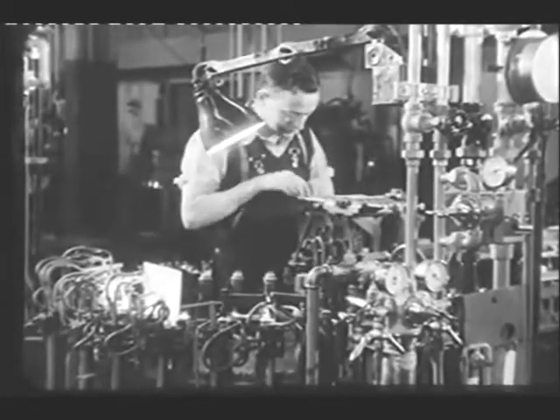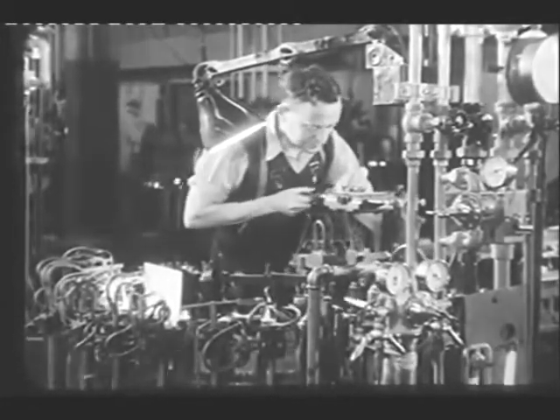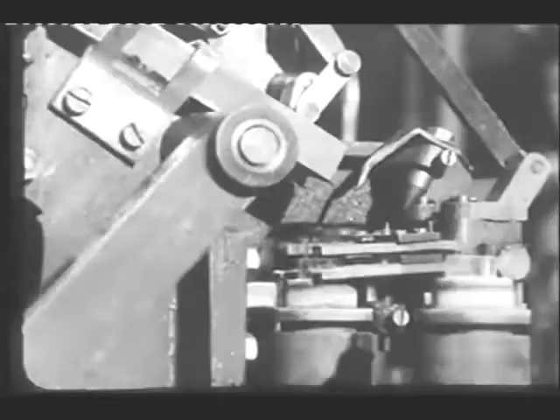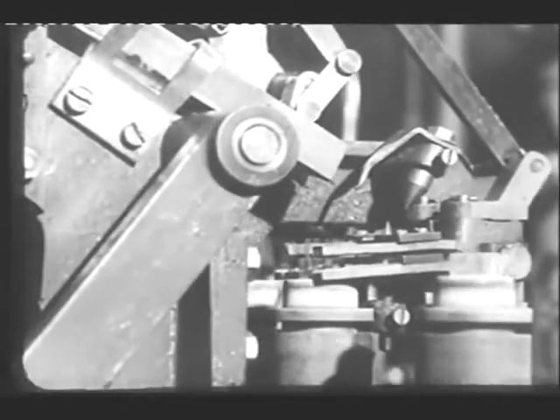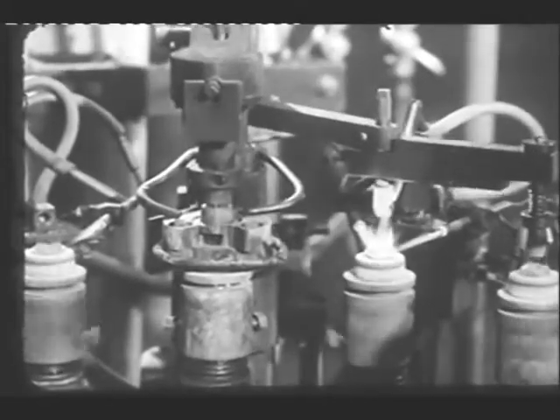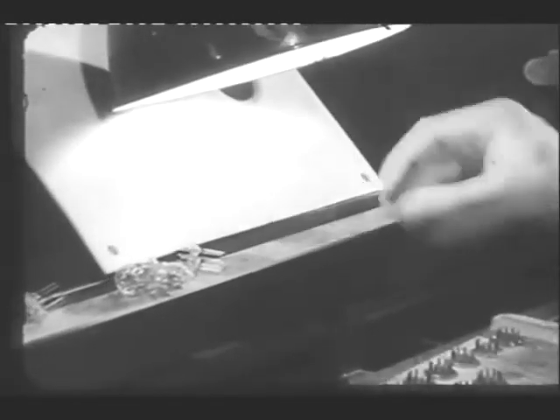The lead-in wires are loaded into the base-making machine and are automatically fed, 9 at a time, into a jig. A glass ring is placed in position round the wires, and the jig is made to revolve under gas flames. The glass softens, and the machine presses it to form the base. When cold, the bases are inspected.